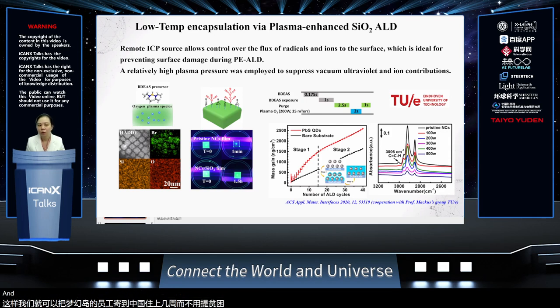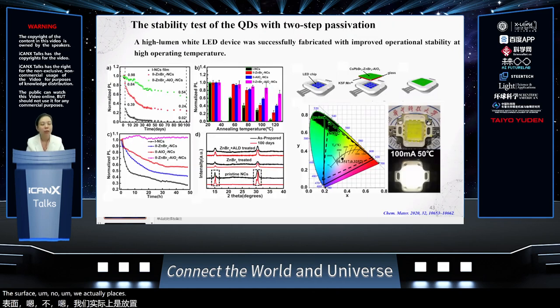And this is normally very hard to believe initially. With this kind of mild plasma processes, we do not deteriorate the ligands, but at the same time passivate the surface at non-reactive places. And similarly, we can utilize this kind of quantum dots. And once we encapsulate them very well, we will be able to adopt them with the LED chips. And it can actually go up to 100 milliamp at 50 degrees Celsius and survive for a long time without degradation. This actually helps to improve the stability significantly.